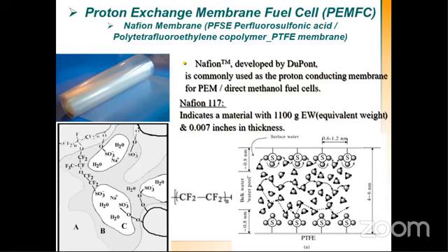There are different codings. Nafion 117 means there is 1100 gram equivalent weight of membrane and 7-inch thickness, 0.007 inch in thickness. So these are different kinds of membranes. If you see on the right corner, perfluorosulfonic acid is basically SO3H based perfluorosulfonic membranes. SO3H means when the desired temperature is obtained, the SO3H molecules start rotating, and in that way proton passes through the channels. This is a membrane. This is another membrane. These are the empty channels which are hydrated, which allows the proton to pass through.